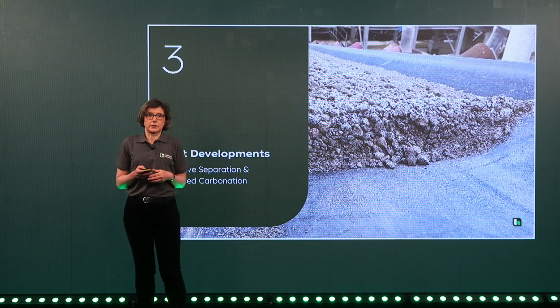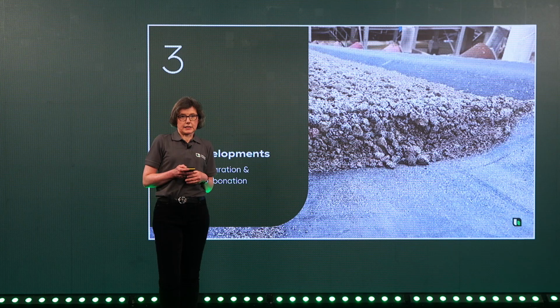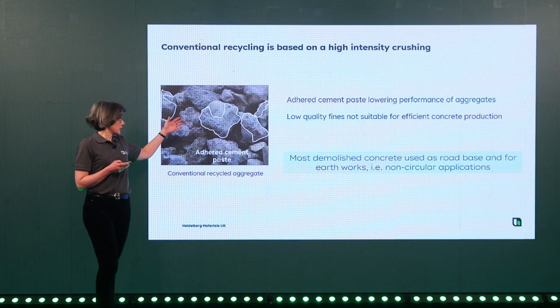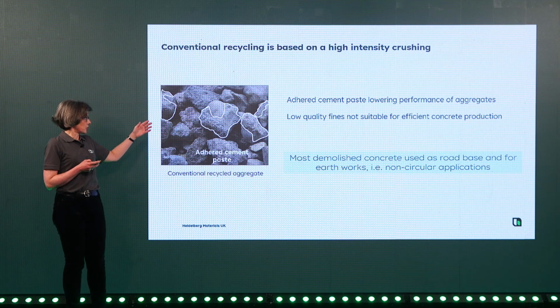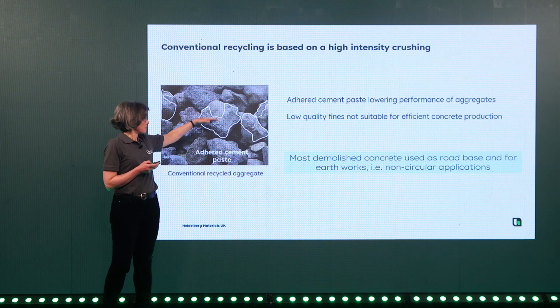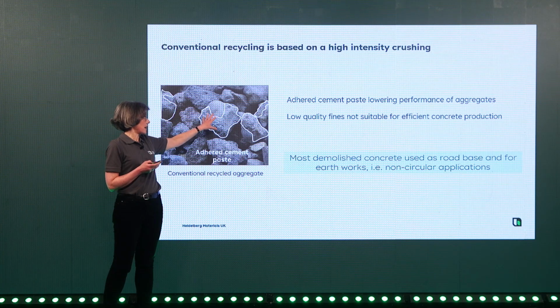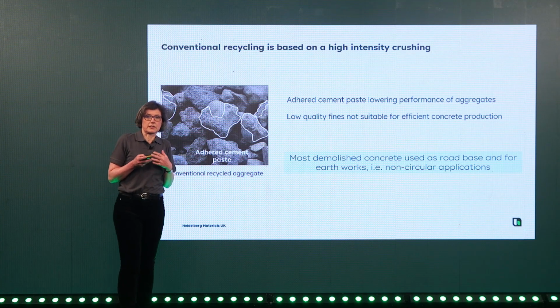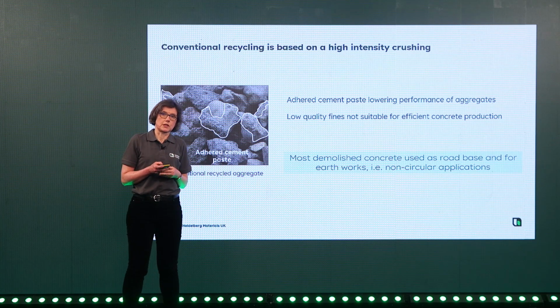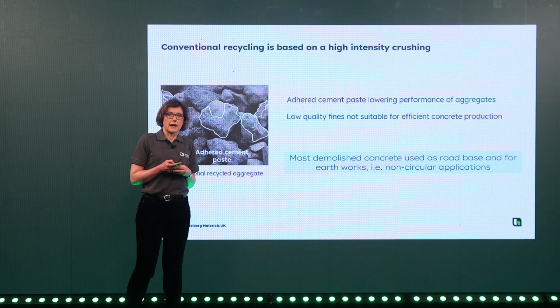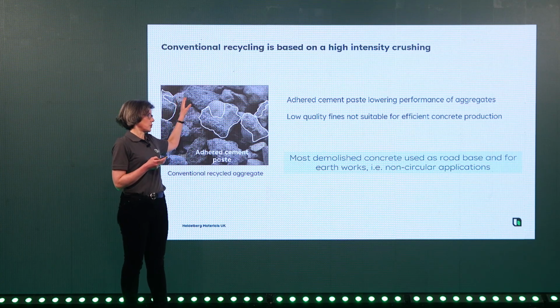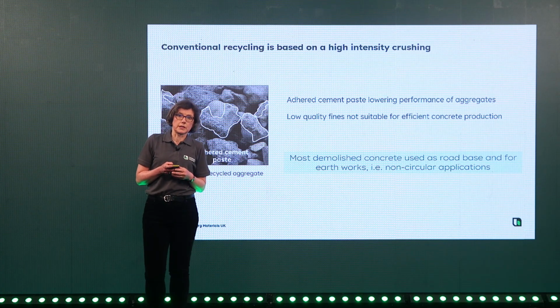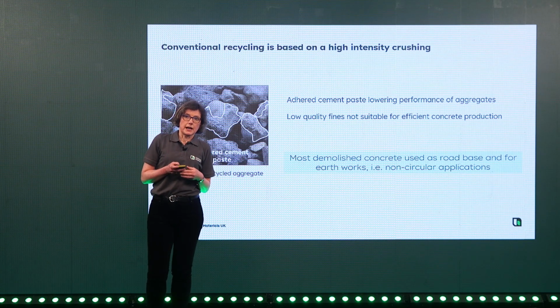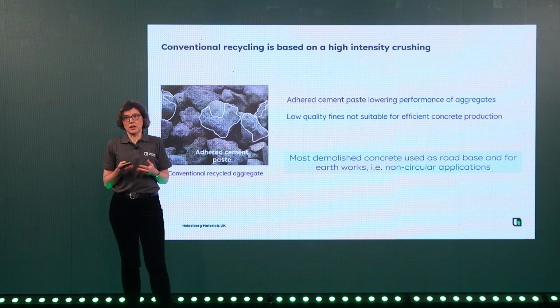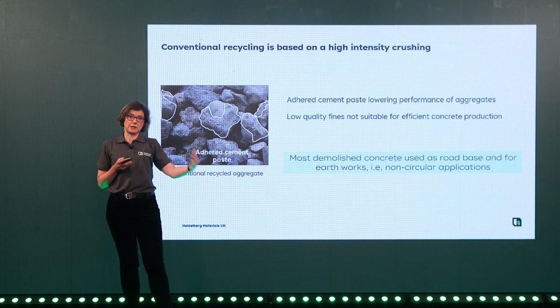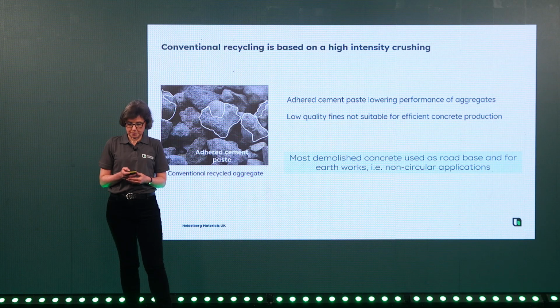Moving from the lab to pilot developments, first of all about the selective separation. This is a traditional recycled concrete, and what you have here is the cement paste still adhering to the aggregates, which means that the aggregates themselves don't give a very good performance in concrete. They increase the water demand, and the fines from this process are also not particularly good for use in concrete. That is why most of this material ends up, for example, as road base or in earthworks, which is not true circularity because it's really being downgraded from its original use.